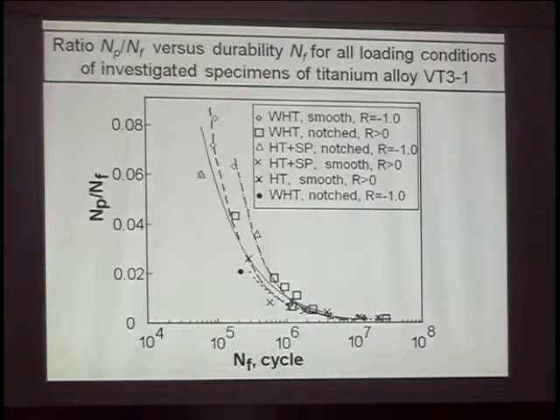If I understood your question, first of all, sorry, I answered only the first part. This curve has been constructed for practice, because in my further analysis I should understand whether I can use the crack growth period, which can be easily estimated from the fracture surface by measuring fatigue striation spacing, to predict how long the life was. Yes, it's really so. It depends on the material state. It's very nice. But another fundamental question is the ratio between the number of cycles during all material cracking and only the second stage, when we can see fatigue striations. You're absolutely right.